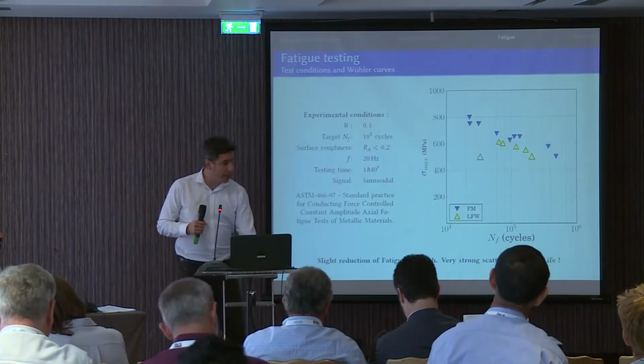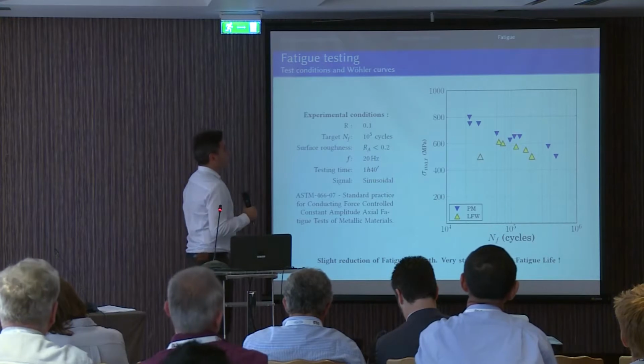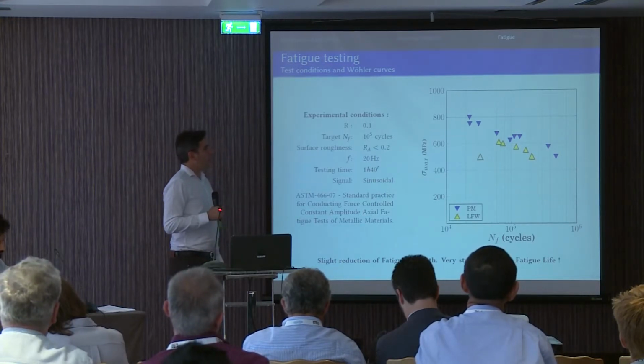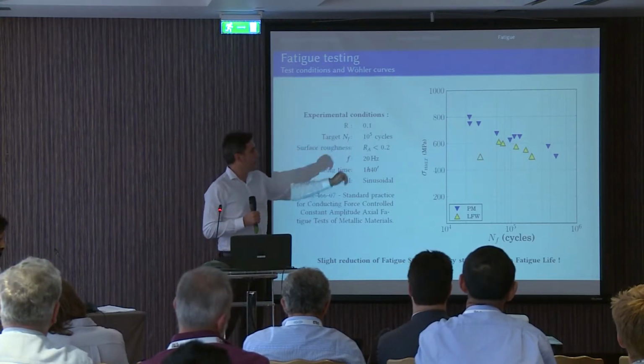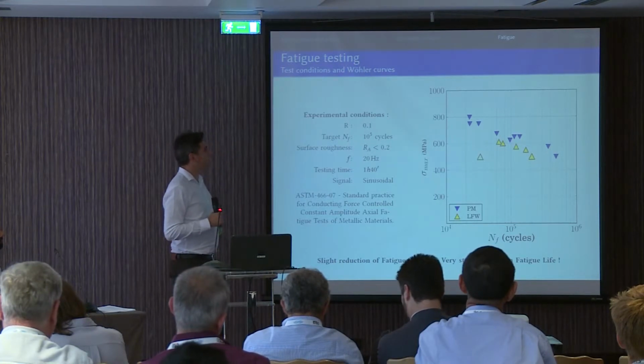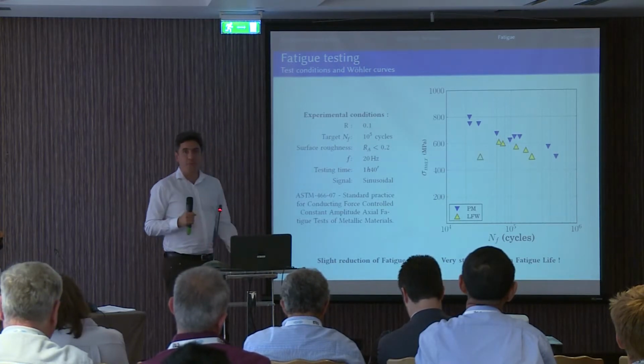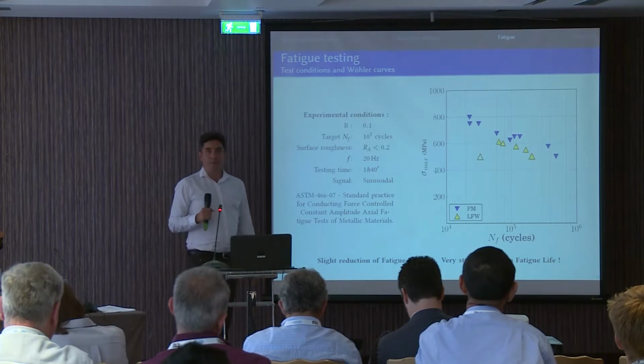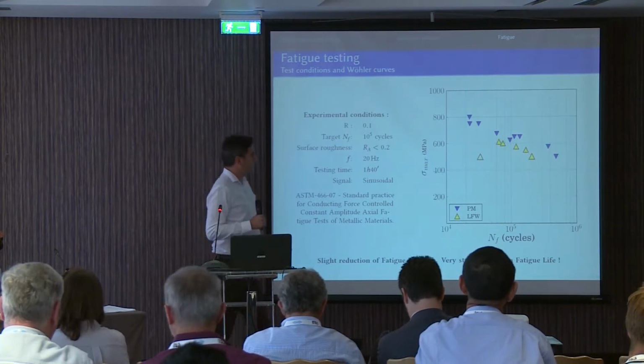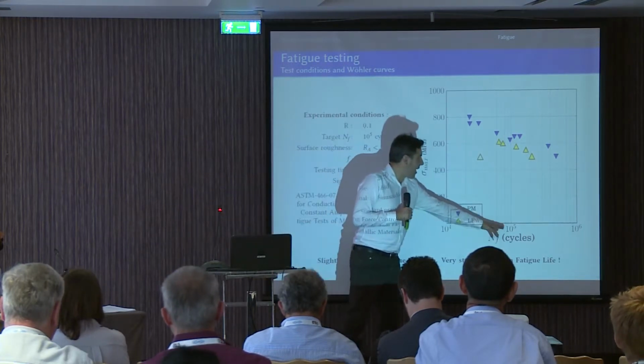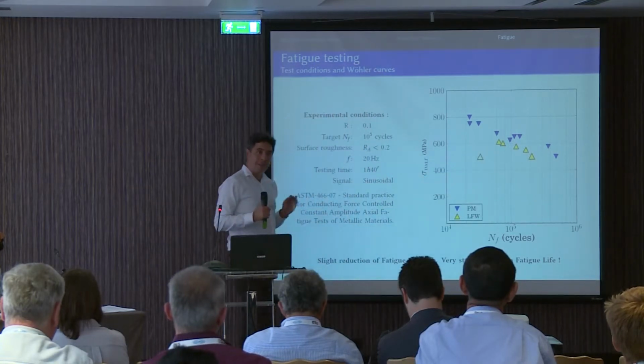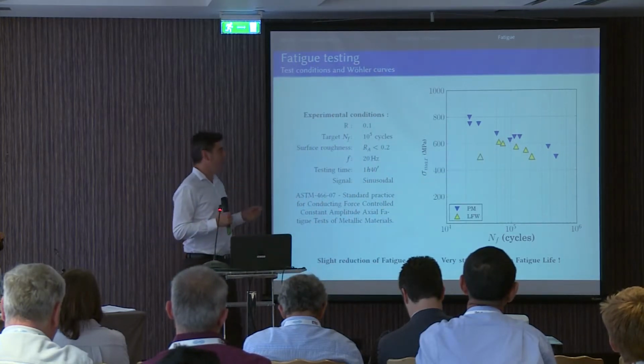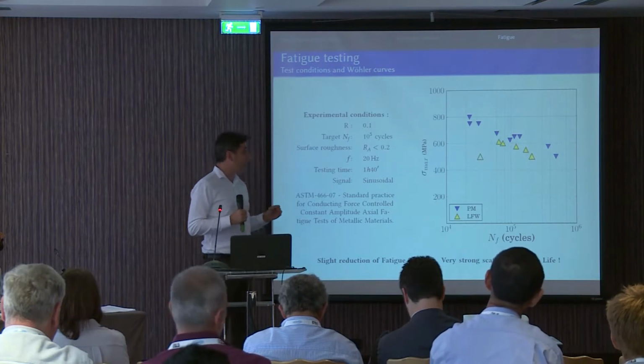So let's study that. Here we have the S-N curve for the parent material in blue and the cross-welded specimen in yellow, with a stress ratio of 0.1 and a target life of 10 to the power 5 cycles. As you can see here, for the target life, the fatigue strength is slightly reduced. We're talking about a fatigue strength of 625 megapascals.